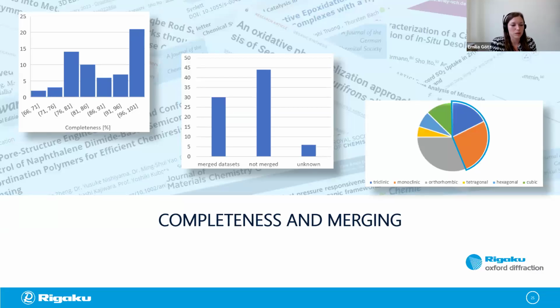And this will increase the completeness and also the redundancy, and it will usually help us get better ADPs in the end. But as you can see, data merging was not necessarily used in all cases, and some even got a structure with a relatively low completeness, below 70%.